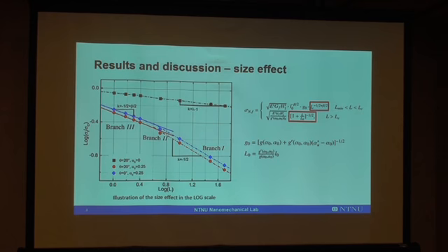So in this figure now, the slope at each point represents the strength of the size effect. Our first conclusion is that the size effect is not so pronounced, not so strong, in the case without pre-crack as in the cases with the pre-crack. Secondly, the data sets for the pre-crack cases are practically parallel to each other, which indicates that the size effect here is dominated by the pre-crack instead of the misorientation.